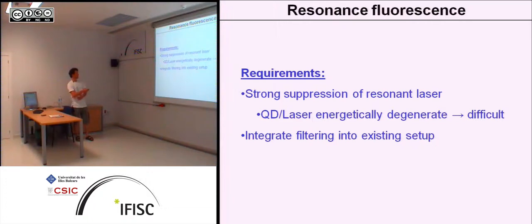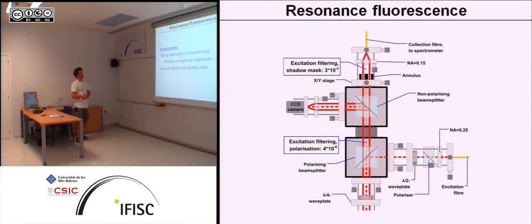And for that we need strong suppression of the resonant laser, which is quite tricky to get to a high enough degree, because you need attenuation of 10 to the 7 or something. And then we also want to integrate it into the existing device we use. So for that we just slightly adapt this typical microscope head we were using and introduce some polarization filtering here.